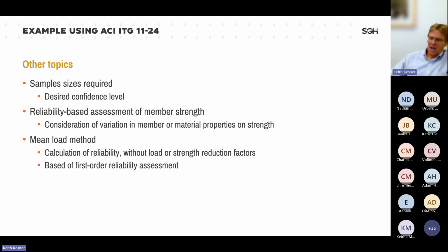And the other thing that ties into that, there's something called the mean load method, which allows us to do a calculation of reliability. We're all familiar with the concept of beta as a measure of the probability of failure of a structure. We can calculate beta based upon average strength values obtained from the structure without load or strength factors, based upon a first order reliability assessment. And there's a nice worked example on how you do that, which is basically a simple way to calculate the probability of failure of a structure. So that's some of the things that are present in the ITG.